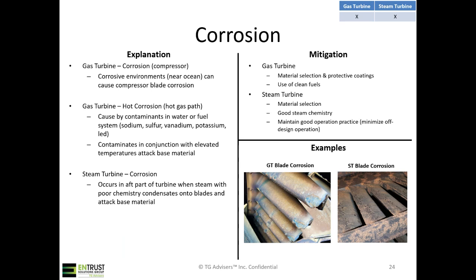Some of these elements that will promote hot corrosion are sodium, sulfur, vanadium, and potassium. And when these contaminants get into the system at high temperatures, that's when it will attack the base material. Steam turbine corrosion a lot of times affects the aft part of the turbine. It happens when steam has poor chemistry and it condensates onto blades and attacks the base material over time. So it's always important to have steam and water in the system with good chemistry.